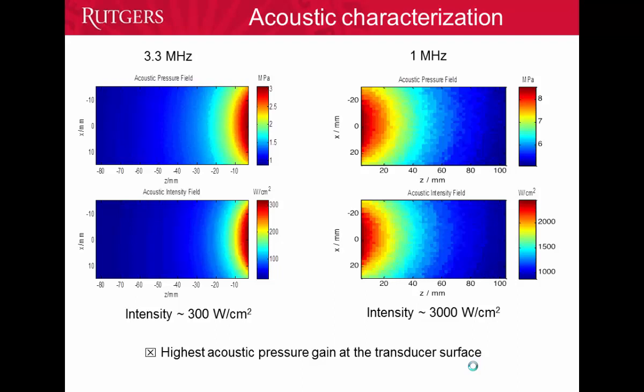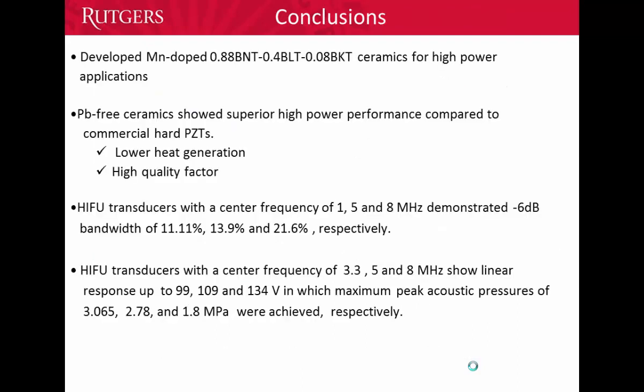Then we measured the acoustic pressure field and acoustic intensity along the z-axis for the 3.3 megahertz and 1 megahertz transducers. You can see that the maximum intensity for the 3.3 megahertz transducer is 300 watts per square centimeter, and in the 1 megahertz transducer we could reach 3,000 watts per square centimeter, which is desirable for HIFU transducers. As a conclusion, we developed manganese-doped ceramics for high-power applications. Lead-free ceramics show superior high-power performance compared to commercial hard PZT in terms of lower heat generation and higher stability of the mechanical quality factor.